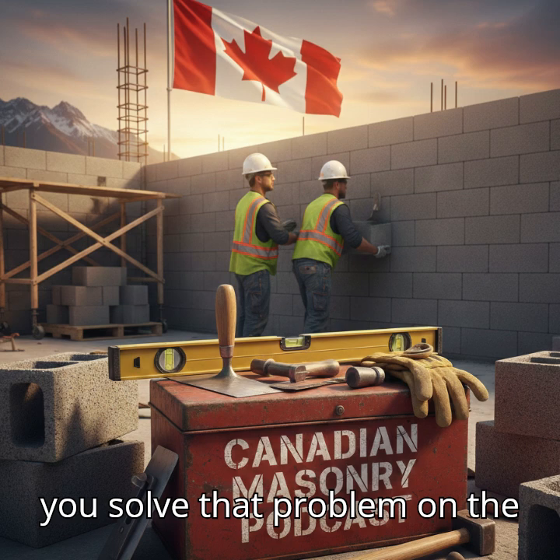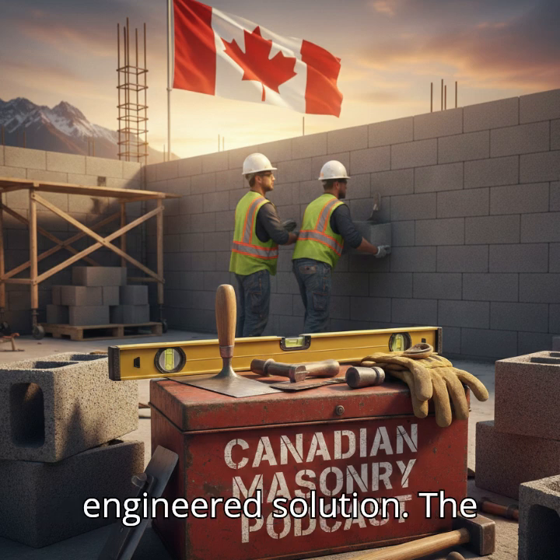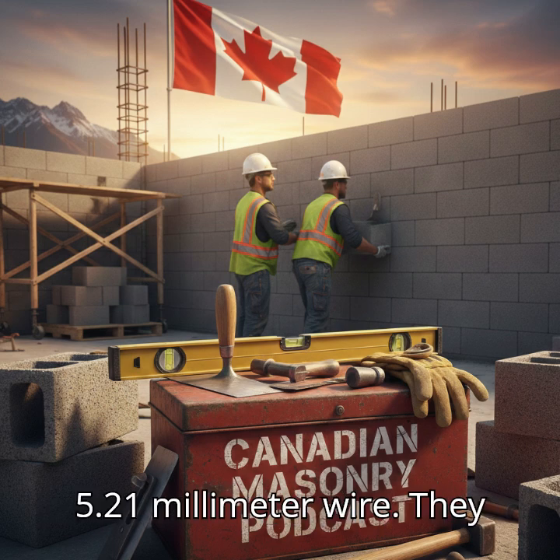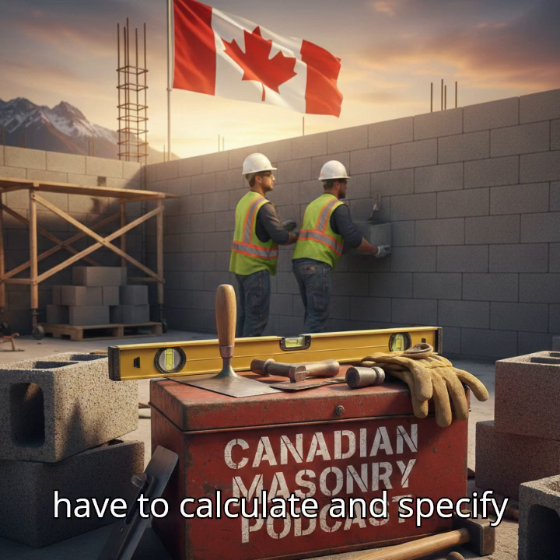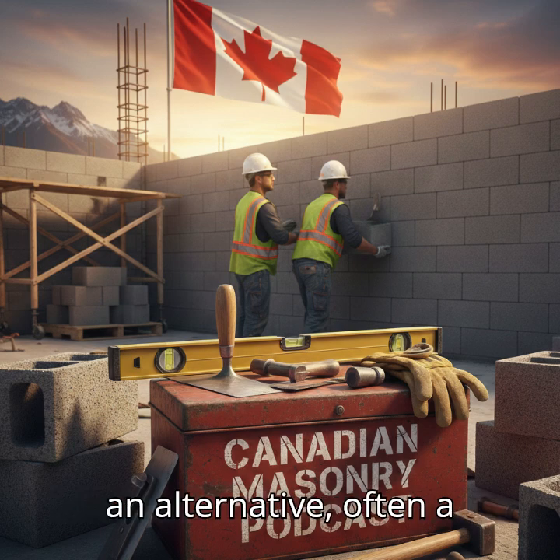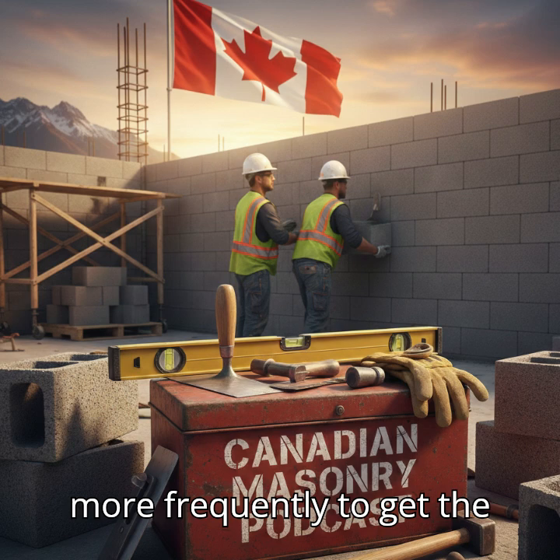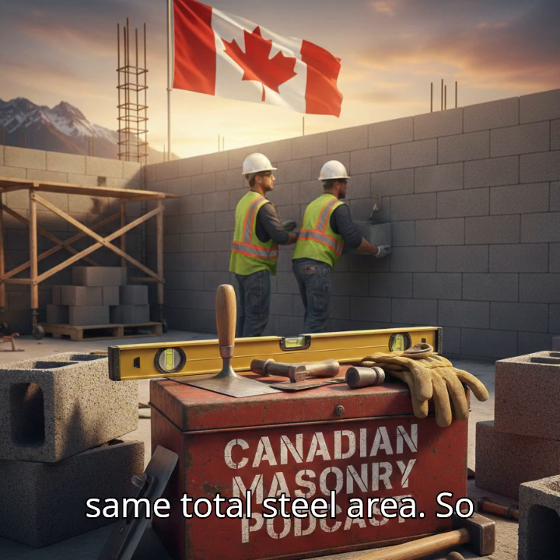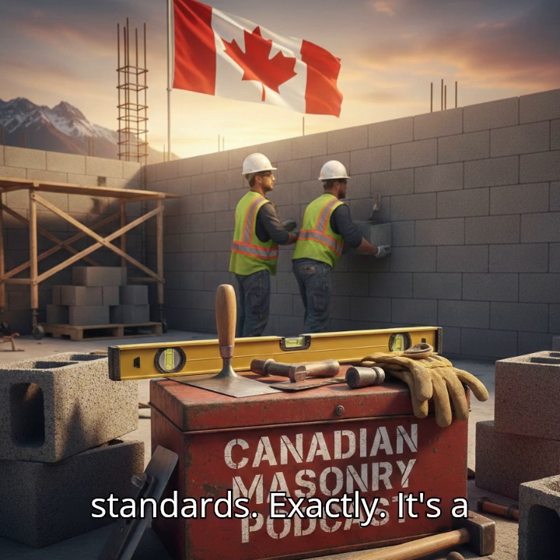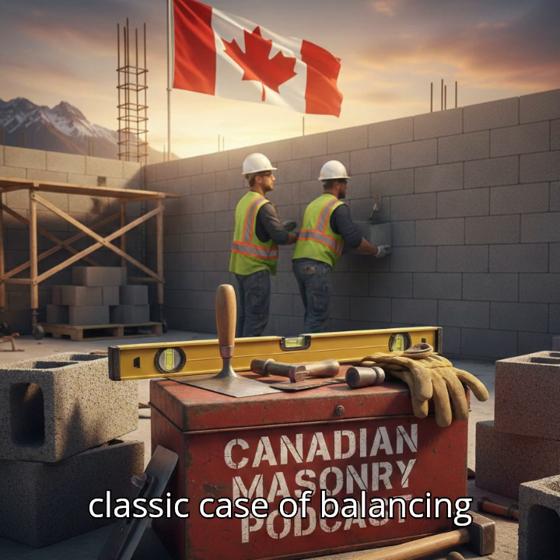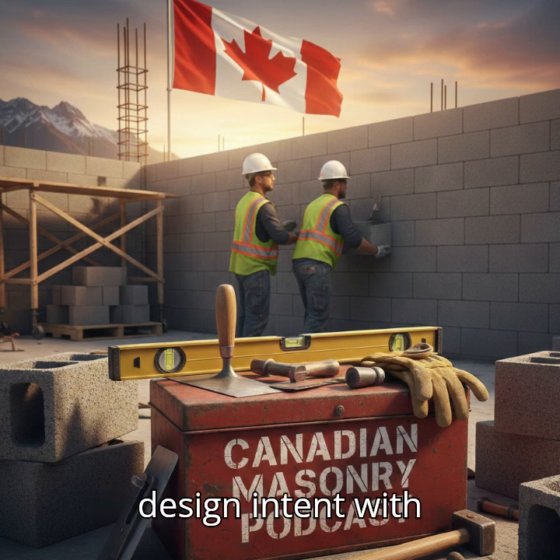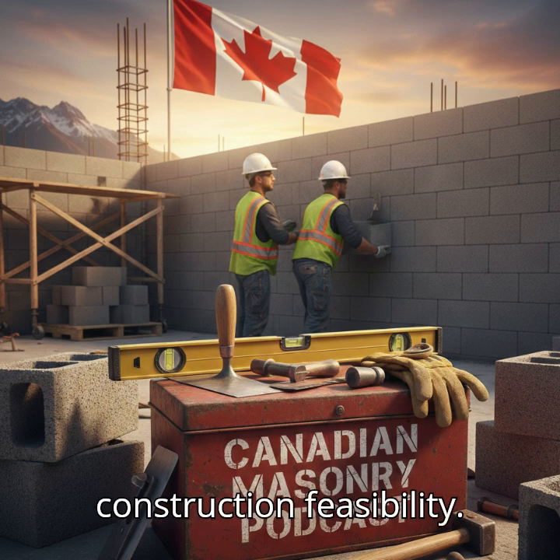How do you solve that problem on the ground? It requires an engineered solution. The designer can't just spec the 5.21 millimeter wire. They have to calculate and specify an alternative, often a smaller diameter wire spaced more frequently, to get the same total steel area. So you're satisfying both standards. Yeah. Exactly. It's a classic case of balancing design intent with construction feasibility.